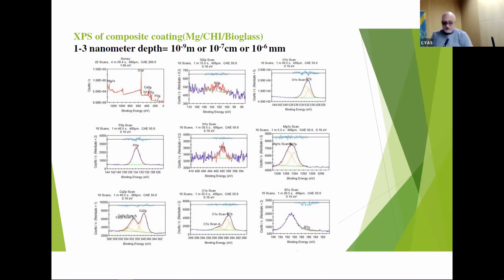Which also means here that, for example, if we see this calcium peak, which is strong, that means you have, for example, 2 types of calcium, which means 2 types of compound. Perhaps tricalcium phosphate or dicalcium phosphate. So, according to the P, we could expect what kinds of product you have.